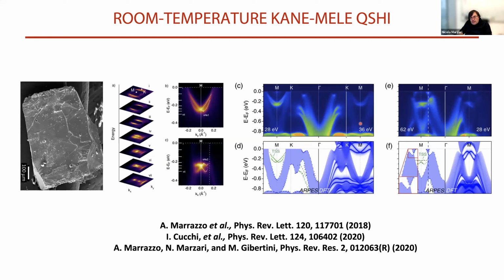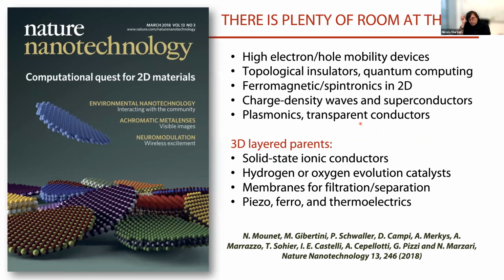We had already predicted that it was quite insensitive to oxidation, proton attack, water. So, it could be manipulated, say, at ambient conditions. And you see exactly now the comparison between theory and experiments, seeing the topological bands that we had predicted. So this was an example, basically, of discovering novel materials for applications. This is a work that is very much in progress. As I said, we keep discovering novel candidates and looking for new properties between those candidates.